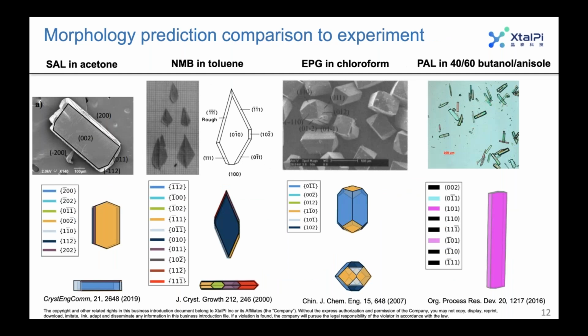Here we have just a few more select examples that show you how this method works. We have SAL in acetone, and this is just comparing the prediction to the experimental morphology. The NMB in toluene, which always amazes me, because it's kind of a strange morphology that's obtained and predicted quite well by the method. Then we have EPG in chloroform, and also PAL in a binary solvent of 40/60 butanol and anisole. So this is a needle-like morphology that we were able to capture.